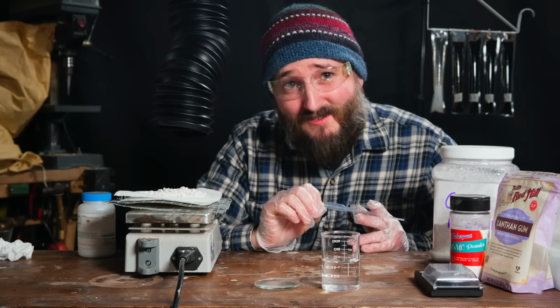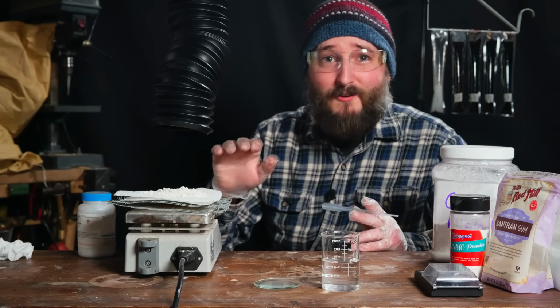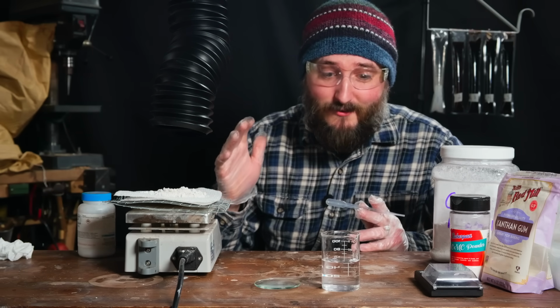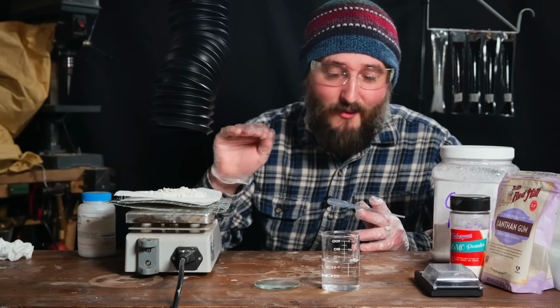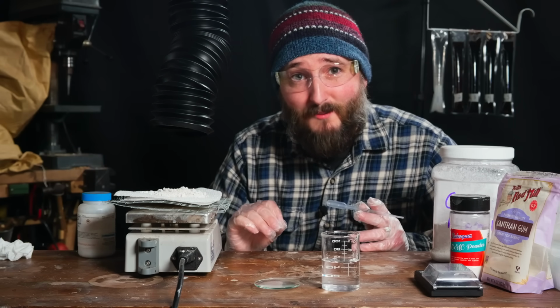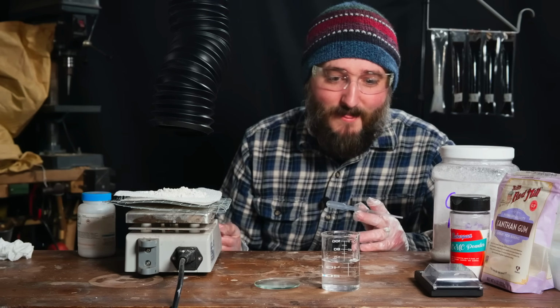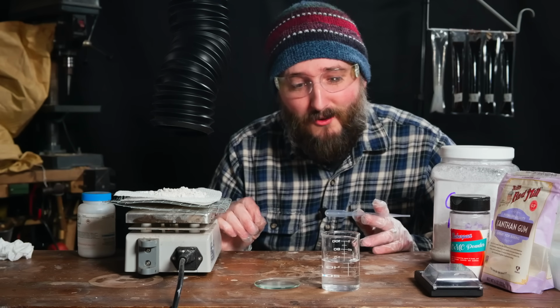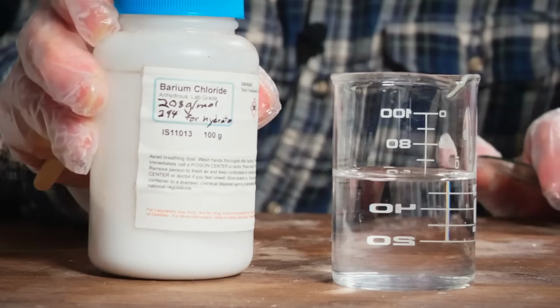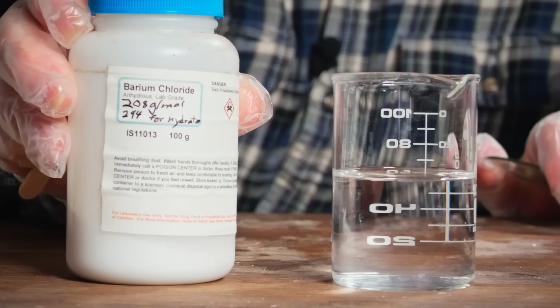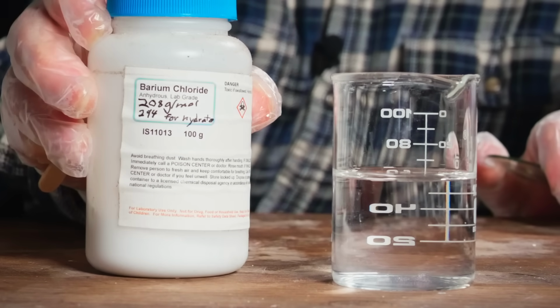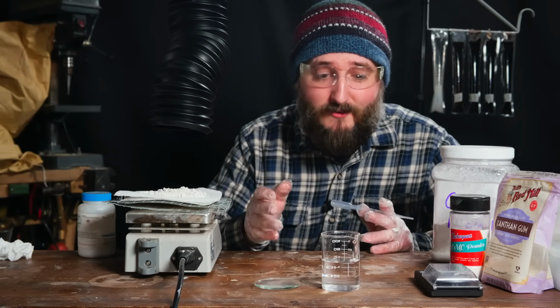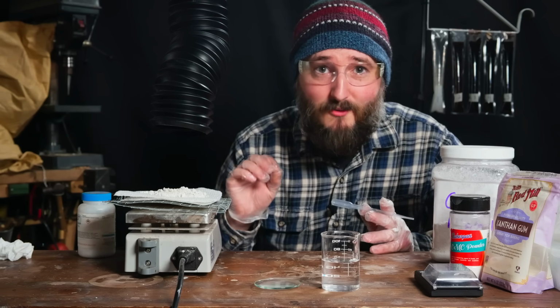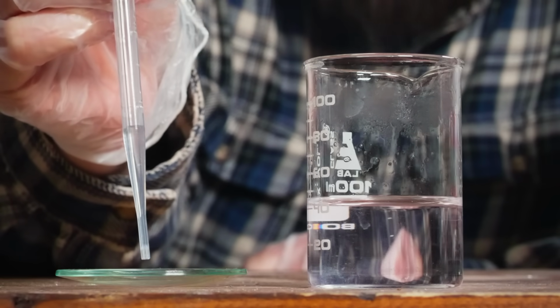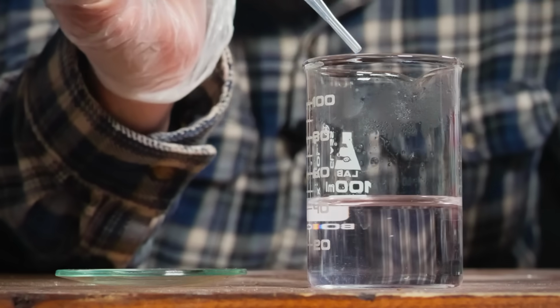At minimum, this does tell me that the end product is fairly pure because any sulfite salts that were remaining in this would have definitely reacted with calcium chloride. Let me try something a little bit stronger. We'll make a solution of barium chloride. That's the standard test for sulfites, and if there are any sulfites present in this, they should definitely react with barium. Okay, barium now.